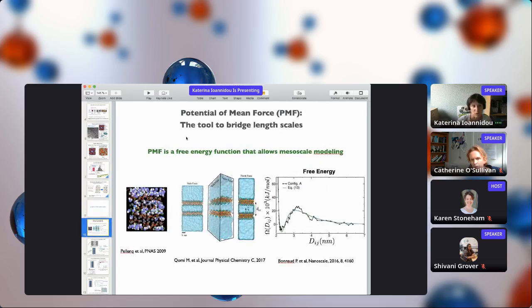A way to do this is to use the potential of mean force. In this simulation work from Qomi et al., we have two atomistic configurations of CSH immersed in water, and using a perturbation theory technique, we can get the thermodynamic potential as a function of distance. Knowing this thermodynamic function, we know exactly the interaction between two particles at specific temperature and pressure. Then we can use this interaction as an input on a molecular dynamics simulation and go to the next scale, having a coarse-grained model at the next level.